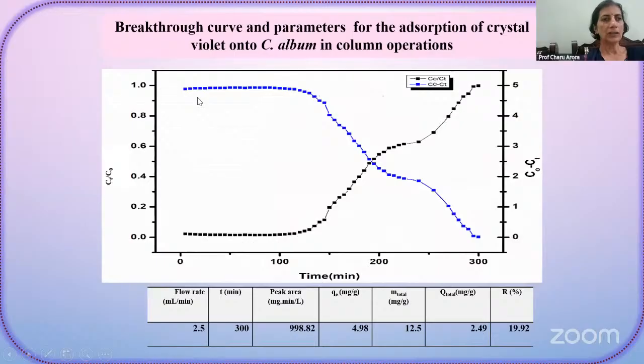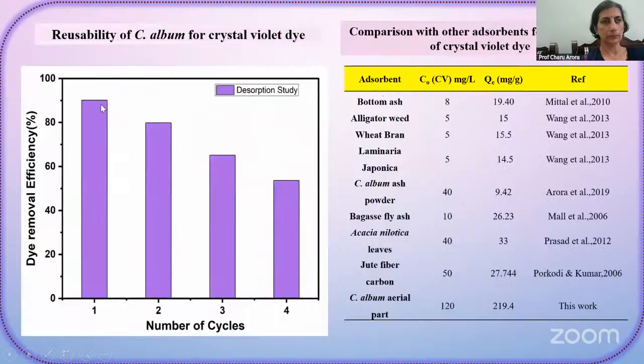And this is the breakthrough curve obtained by column, indicating a very good removal takes place in 300 minutes. Again, this material can be reused. Initially, the removal efficiency was more than 90%, and after 4 cycles, it was more than 50%. It can be used repeatedly again and again.